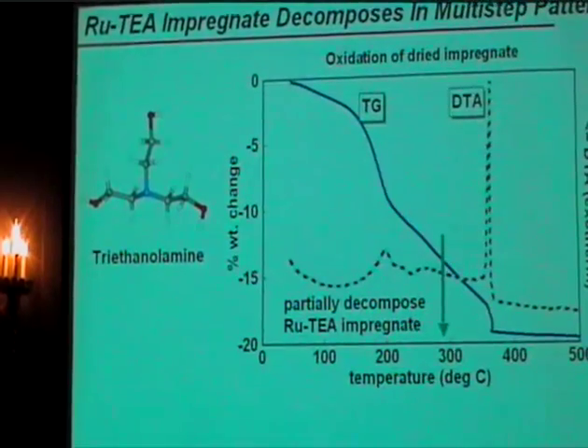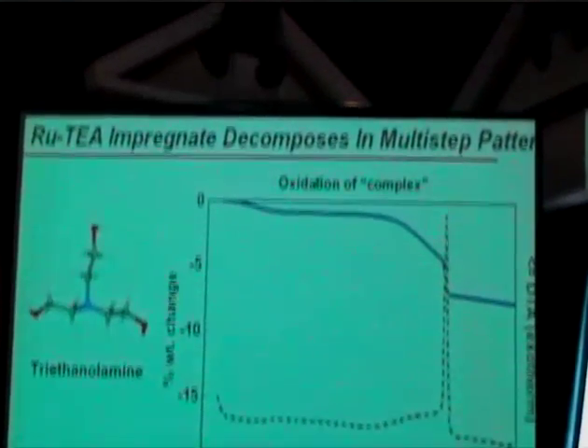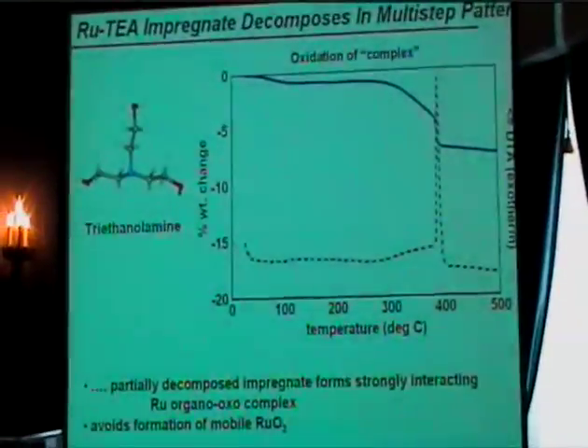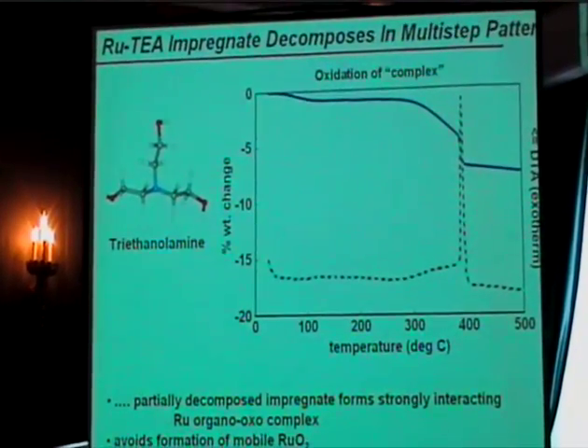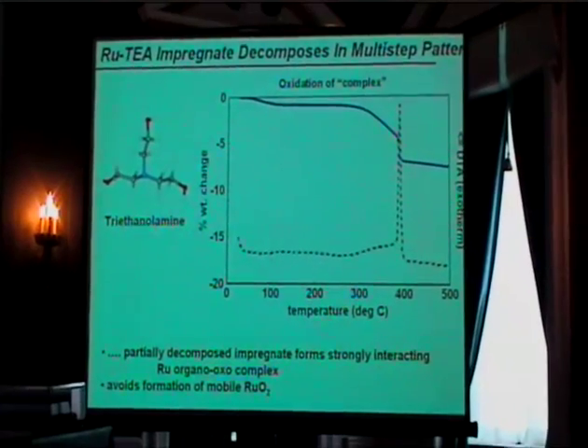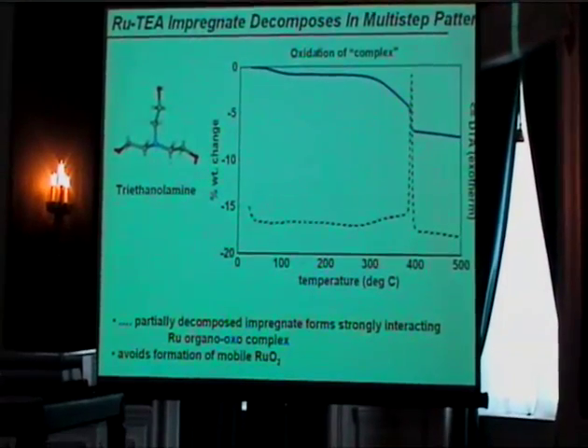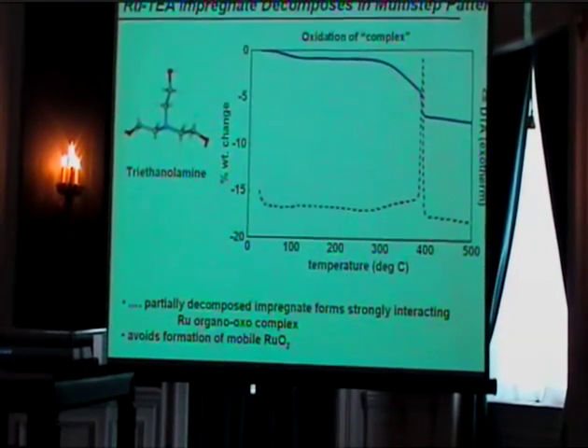So what we did was take this and actually heat to temperatures here between maybe 275 and 300 C to go through the first set of exothermic steps, but maintain what we have over here. Okay, so this shows now, if you do that, you heat this at 300 degrees C, and then if you were to come back and do it again, you see all the stuff in the beginning is gone. And then you do have this very stable complex that's left of the partial decomposition of the triethanolamine ruthenium complex that you impregnated with. And what we'll find, and what I'm going to show you, is that this actually forms a very strongly interacting complex with the silica. Because it interacts strongly with the silica, it tends to disperse it very nicely. And it avoids now going through the ruthenium oxide precursor. Don't oxidize this fully. You keep that organic complex there. Okay, and we're going to see that that's important.